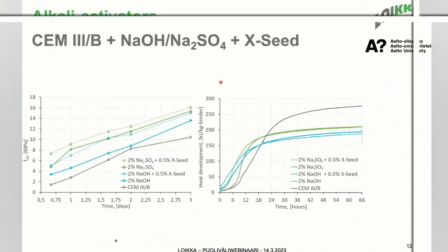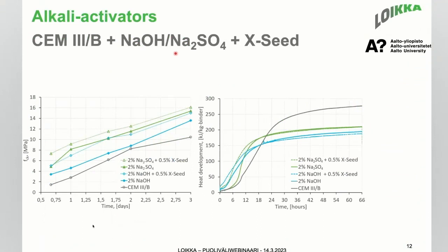To increase the dissolution of the slag, we also added sodium sulfate, and we tried to add X-Seed to provide additional nucleation sites. The results showed that CEM 3B with addition of sodium sulfate and X-Seed showed the best compressive strength. We can see the same pattern in the temperature development. Sodium sulfate with X-Seed, this dotted line, showed the highest temperature development among the activated cement pastes.